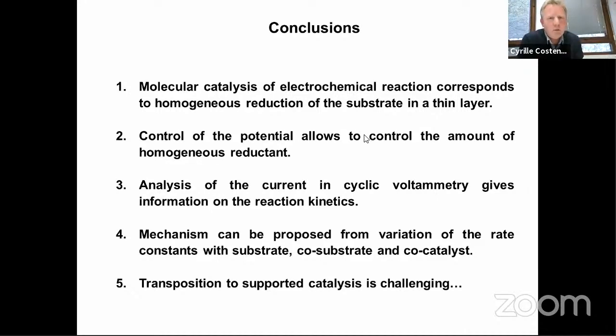I would say, of course, I didn't mention that, because I mostly consider the case where there is no limitation by diffusion of the substrate. But if there is some limitation by diffusion of the substrate, in the equations, the ratio of the diffusion coefficient of the catalyst over the diffusion coefficient of the substrate appears in the equation. I didn't show that, but it's possible to take that into account. Of course, if your catalyst is an enzyme, so a big molecule, it will not diffuse. So then you will be closer to a situation where you have a monolayer of the catalyst.